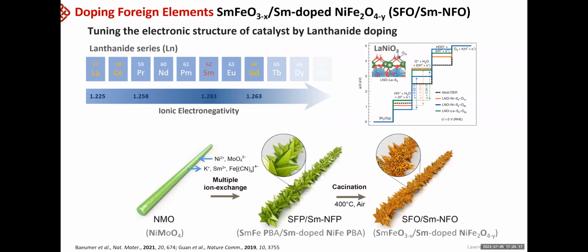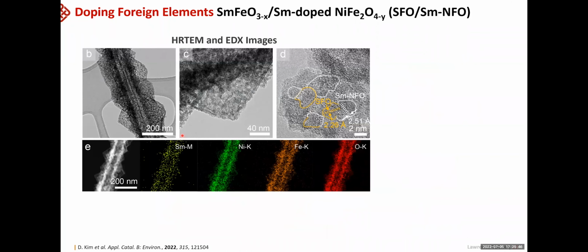And we used exactly the same system to control the doping and the interface at the same time. So in this case, we introduced samarium at the same time to form the interface of the PBA species, and then we calcinate to form them into samarium ferrite and samarium doped nickel ferrite species. So SFO interfaced with samarium doped NFO. The TEM image shows that they are showing a sort of nanopyramid structure composed of two species. We actually found SFO and samarium doped NFO species. They are forming small domains.